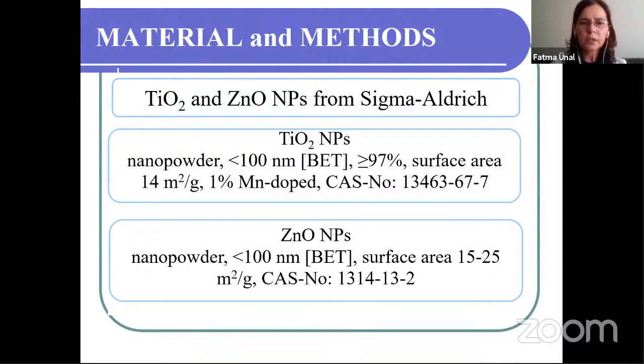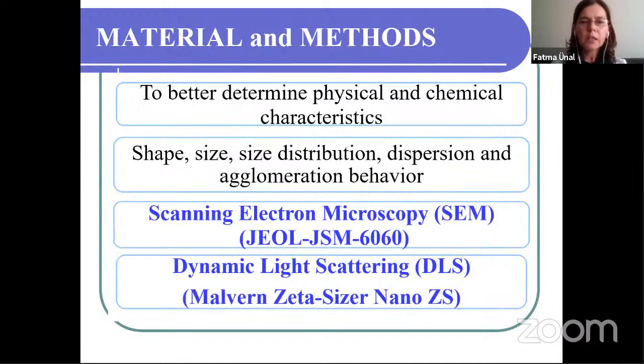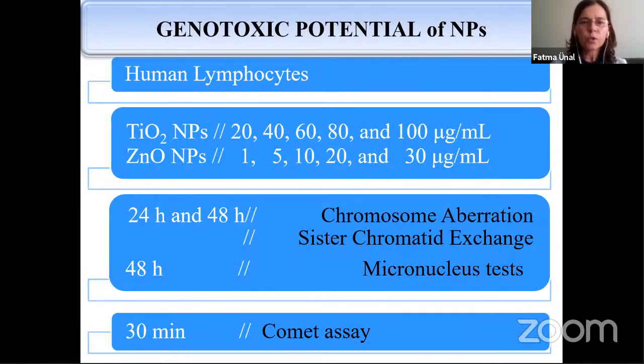The materials we used were obtained from Sigma. Some of their characteristics were given in this slide. However, to determine physical and chemical characteristics, scanning electron microscopy and dynamic light scattering were also used in this study. To determine genotoxic potentials of nanoparticles, human lymphocytes were treated with 5 different concentrations of both nanoparticles for 24 hours and 48 hours in chromosome aberration, sister chromatid exchange, and micronucleus tests. In comet assay, 30 minutes were used.